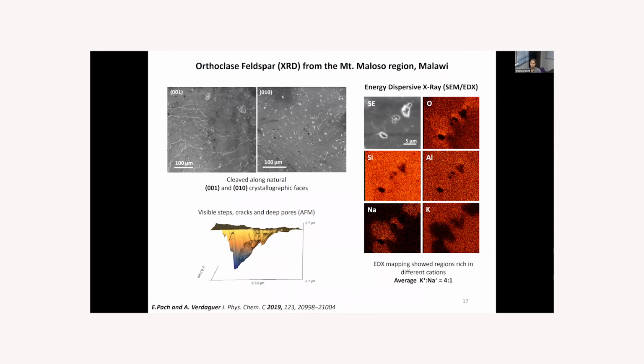So we've also studied orthoclase feldspar from the Mt. Maloso region, Malawi. This is a special case where we could have the 001 face and 010 face and compare them. They were cleaved along the natural crystallographic faces. We usually characterize the surfaces by energy-dispersive X-rays, AFM, XPS, and XRD also. And here you can see at the EDX the non-uniform ordering of the sodium and potassium on the surface. You can also see the pores where the transition of sodium and potassium on the surface were visible.